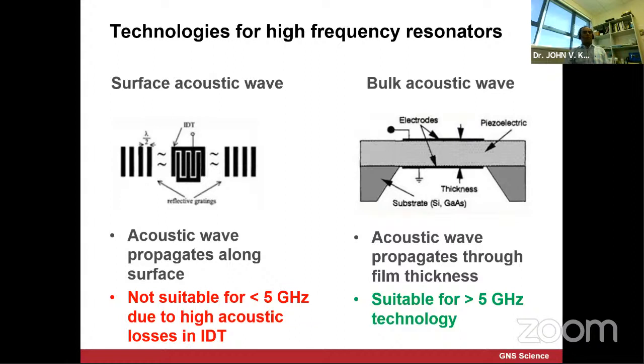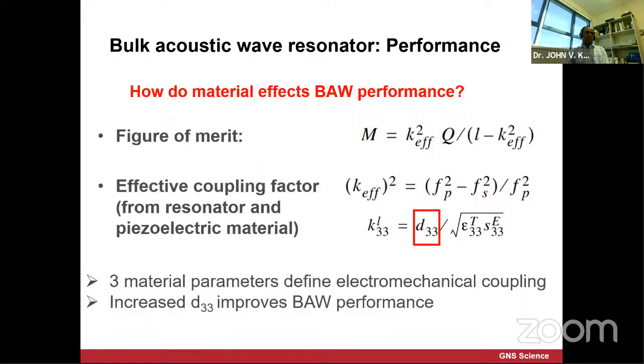But we have been looking at the bulk acoustic wave, where the wave can propagate through the film thickness. This is more suitable for beyond-5G technology applications. But in context to a material scientist like you and me, what does that mean? If we look at bulk acoustic wave resonator performance, what is the key property that affects it? There is a term called figure of merit, a complicated formula, which is equal to the piezoelectric coupling K33, K squared EF. But in the piezoelectric material, the key parameter that determines the performance is D33. If you can increase D33, you can improve the bulk acoustic wave performance, which leads to increased frequency.